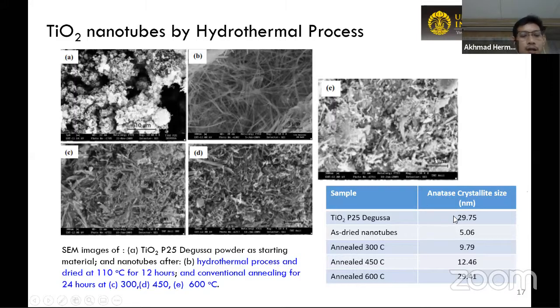But when we improve the crystallinity by subjecting them to calcination, C, D, and E, we can see that the nanostructure has collapsed already. At 300 degrees Celsius, the nanotubes, like wire forms, are still observed, but many of the tubes have collapsed here, forming this kind of aggregation. And at higher temperatures, at 450 degrees Celsius and 600 degrees Celsius, the nanotube structure has totally collapsed.